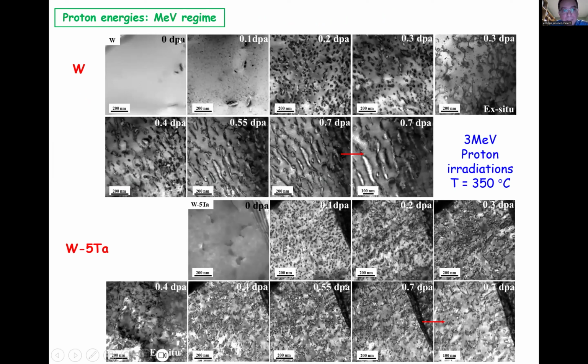We also use proton beams, not to insert hydrogen, but as a surrogate of neutron damage, with the idea that we put enough energy in the material to cause radiation damage and displacement of atoms in the microstructure. But the protons are outside the area that we are analyzing. Now, those black dots that you see here as a function of dpa, or radiation damage, are not bubbles in this case. They're called dislocation loops, which are lattice defects that can move and evolve, and they create this rafting. That rafting of those elongated structures has also been observed in tungsten with neutrons. So it's a good surrogate to use protons for neutron damage. If we put in a little bit of tantalum, you see similar features, but you don't see those elongated structures at higher fluences or damage.